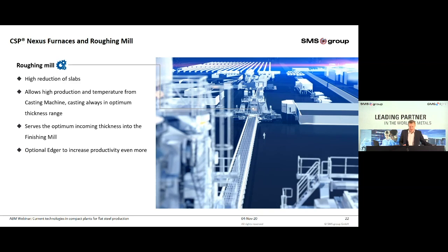The roughing mill of the Nexus plant is capable of reducing the slab thickness to an optimum incoming thickness to the finishing mill. It allows the caster to always cast at optimum casting thickness in terms of productivity and temperature. Productivity can be increased even more by the use of an edger in front of the roughing mill.